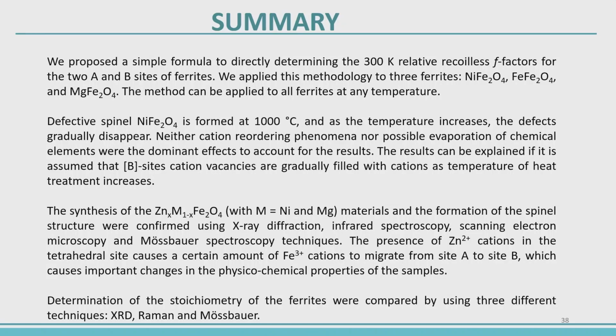But there are more methods, not only that, SAXS, neutron diffraction. There are many methods, and we need to compare because we have noticed that not all the results are sometimes comparable. So we need to take care of that. But it's good to have a comparison of the different methods and to see how the stoichiometry or the cation distribution in the two sites can be determined.